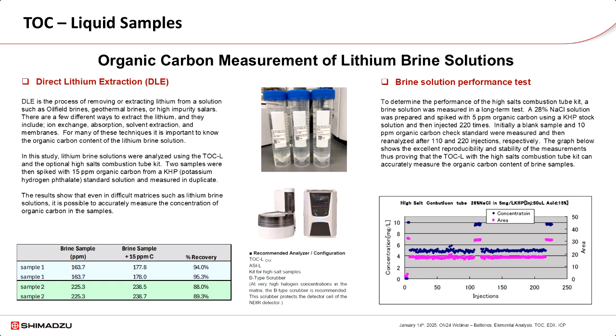For many of these techniques, it is very important to know the organic carbon content of these lithium brine solutions. For this analysis, the TOCL instrument was equipped with the high salt combustion tube and additional B-type halogen scrubber. 2 different lithium brine solutions were first measured neat by the instrument. Then, an aliquot of each sample was spiked with 15 ppm organic carbon and analyzed in duplicate by the instrument.